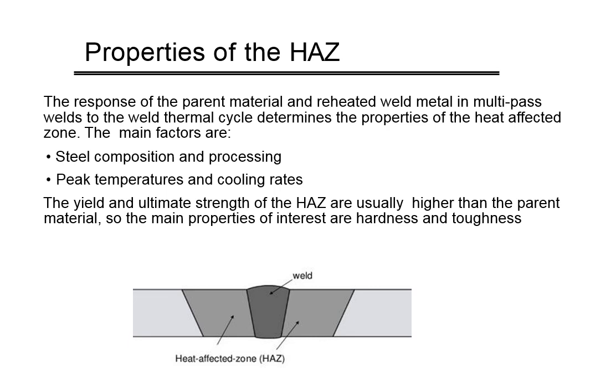So this is just telling us that you got to watch that, because with a weld, there's a thermal cycle, right? You're heating the material up, you're cooling it down. You're heating it up, you're cooling it down. Let's say your guys go away for lunch. It cools all the way back down to room temperature. You preheat it, and then you weld like hell for a while, a few hours, and you heat that piece of metal up, and it cools down, and it heats up, and there's a lot of stresses that are introduced into that piece of material. So that's why we worry. And it's not just the weld we're worrying about. We're worrying about the heat affected zone. How wide's that heat affected zone? Are we watching our heat input into that material? What do we got really going on there? So, and we're talking about the yield and ultimate tensile strength are usually going to be higher than the parent material in this.